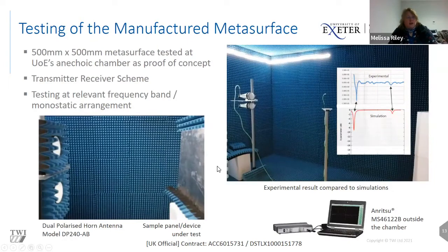We then went on to test our 0.5 meter demonstrator panel at University of Exeter, and we're actually able to show that the experimental results that we got matched reasonably well with the simulation. So this has basically opened up a new processing route for achieving metasurfaces at scale. And I think one of the things to highlight with this project is that we did this in a very rapid time frame.